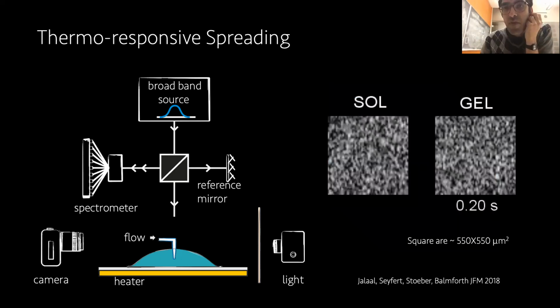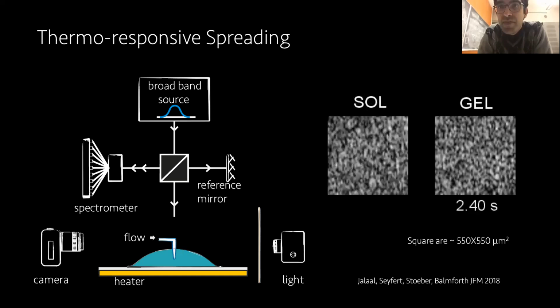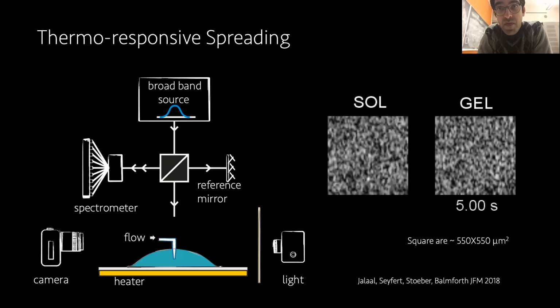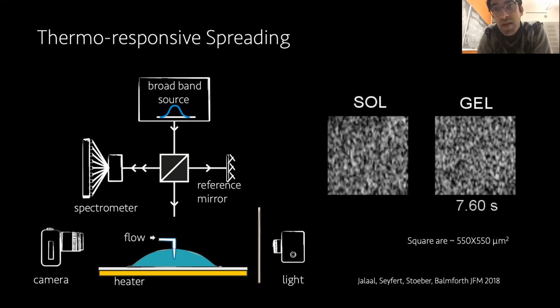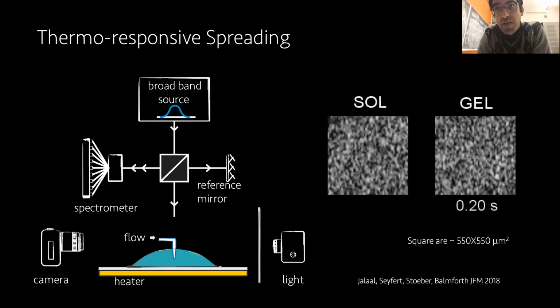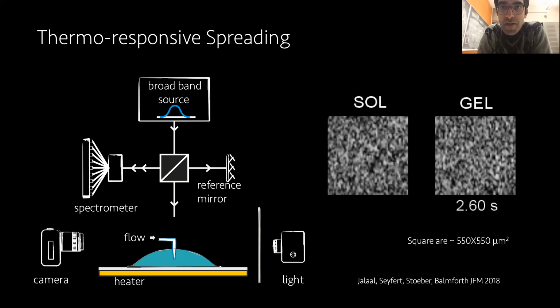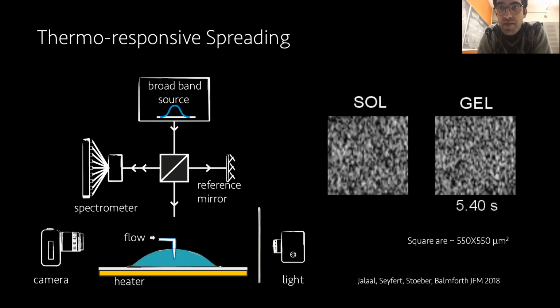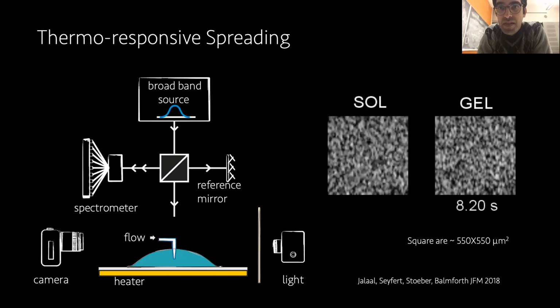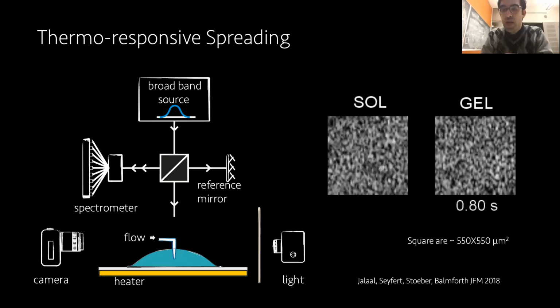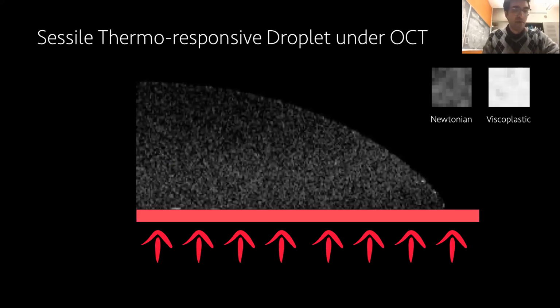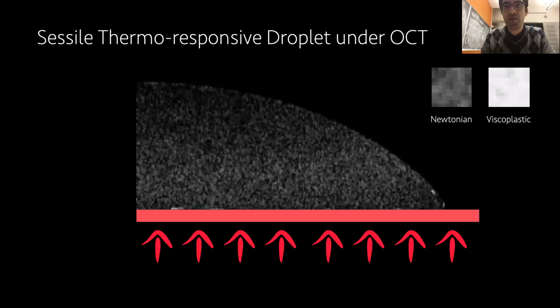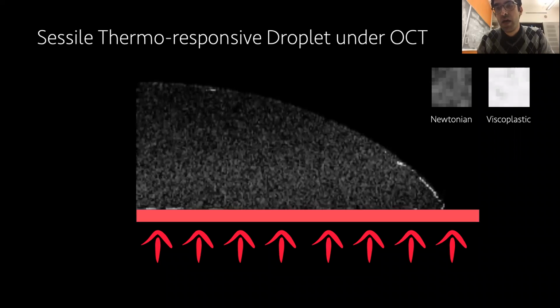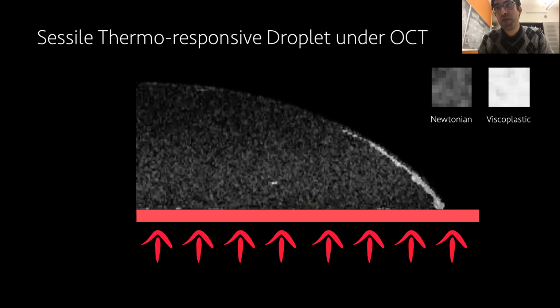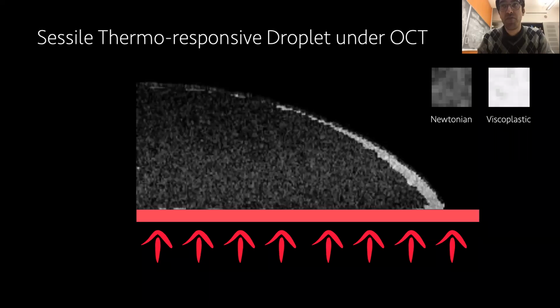And this is the type of dynamical signals that you get. On the left is low temperature, so my fluid is Newtonian. And on the right, you see the high temperature viscoplastic ones. You don't see the particles, but you see their macroscopic manifestation in this dynamic speckle pattern. Okay, so here is one example. This is a droplet heating from below. We did cross correlation to find out where the fluid turns to gel first, so where we become viscoplastic first.